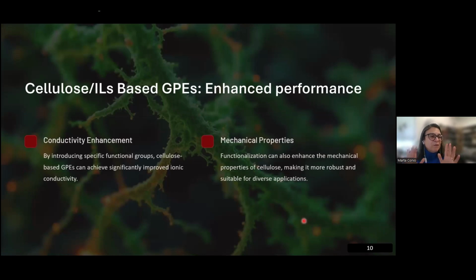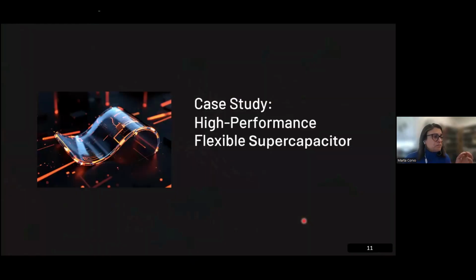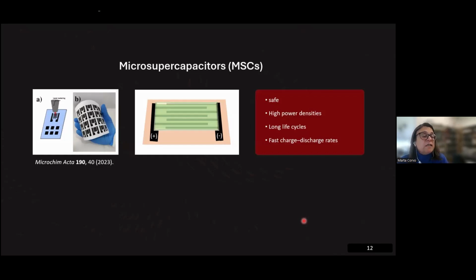And we have been doing this for quite some time, and I'm going to show you an example on how to do this. So in this work, we have been joining these two fields, cellulose-based and ionic liquids, in the prospect of having this conductivity enhancement for the gel polymer electrolytes, and also at the same time to have the enhancement of the mechanical properties. So we can functionalize cellulose. It's not the easiest or most regular task, but it's possible. And by functionalizing the cellulose, it's possible to make composite materials from cellulose and ionic liquids and/or polyionic liquids. So I'm going to show you this case study where we developed some gel polymer electrolytes for micro supercapacitors. So the micro supercapacitors that are shown here, done in collaboration with Dr.